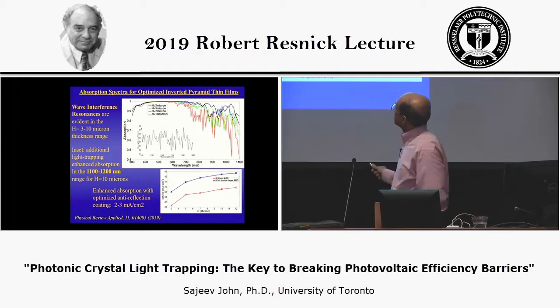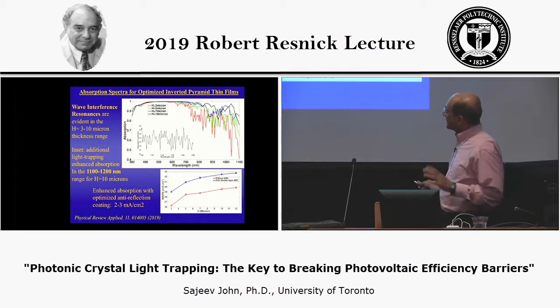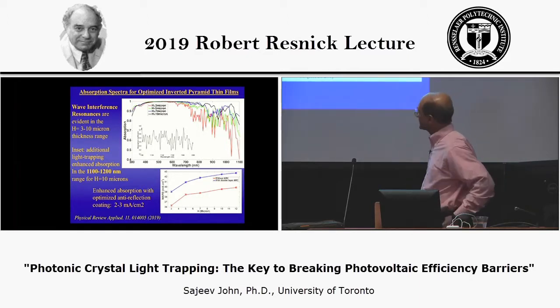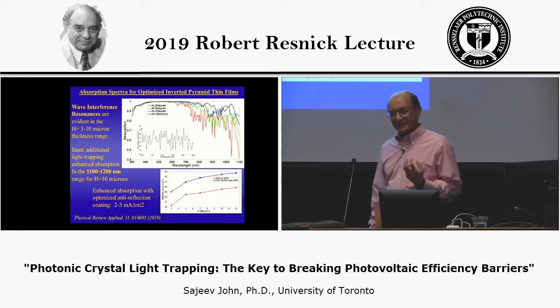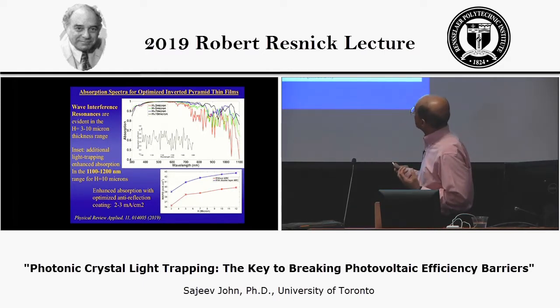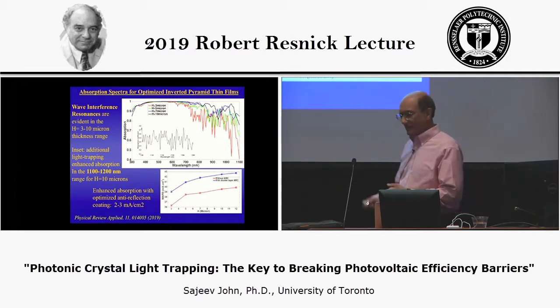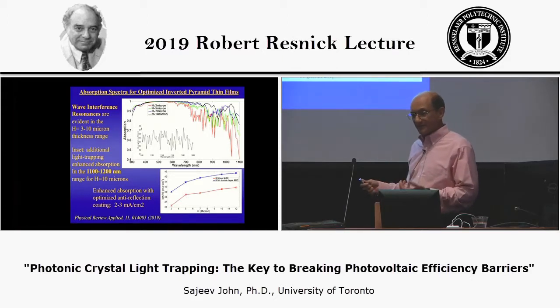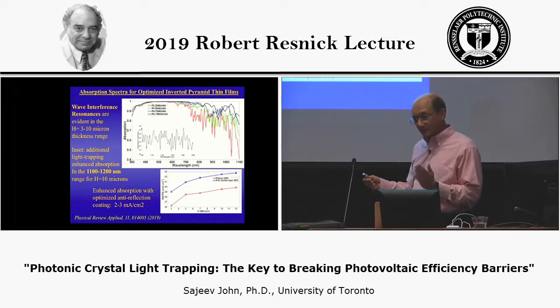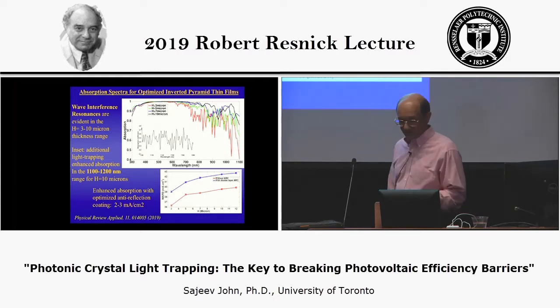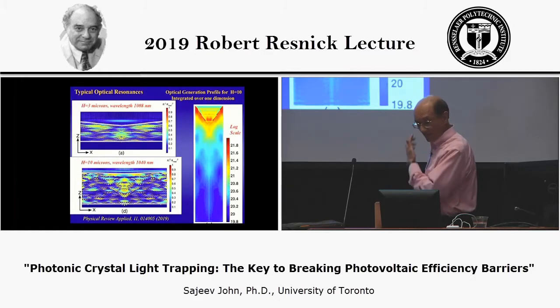In addition, we discovered that in the 1100 to 1200 nanometer range, which is very close to the indirect band edge of silicon, the light trapping effects are so effective that a significant amount of sunlight is still absorbed. So this is the absorption coefficient from 1100 to 1200 nanometers, in the region which would almost require phonon-assisted absorption, even into what's called the Urbach optical absorption edge of crystalline silicon. And that as well can contribute to the overall efficiency of a solar cell with this type of light trapping mechanism.